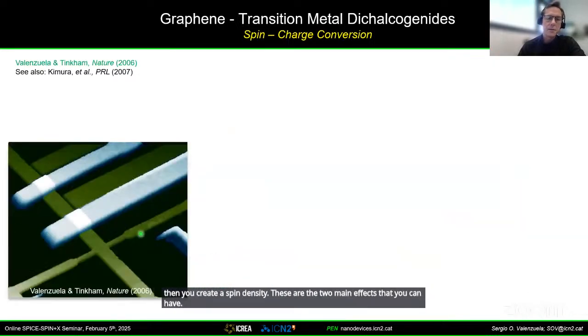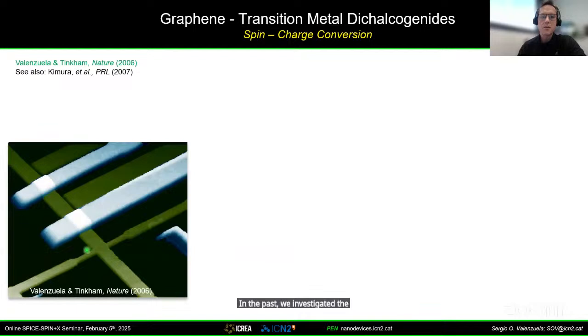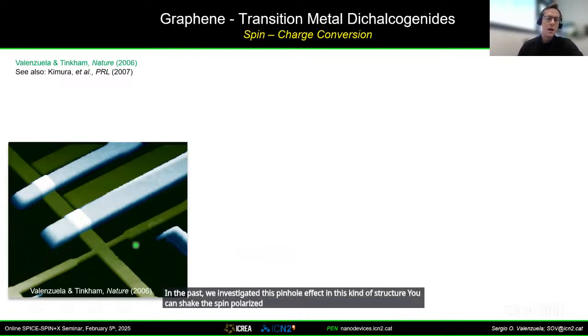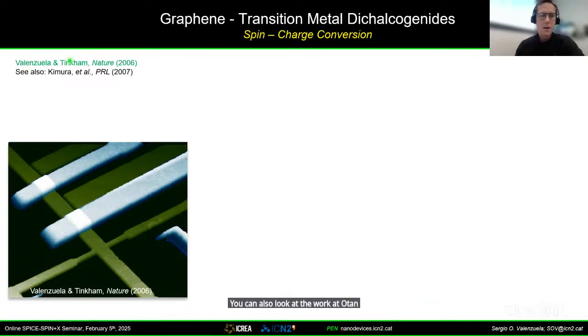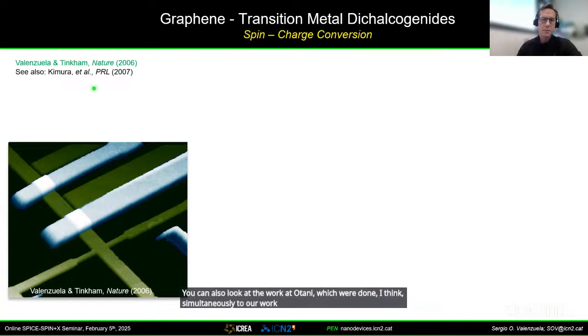In the past, we investigated the spin Hall effect in this kind of structure. You inject the spin polarized electrons from here, and you measure the voltage in a kind of Hall cross by the inverse spin Hall effect, or you apply a charge current here, and you measure the spin signal here. You can also look at the work of Otani, which was done, I think, simultaneously to our work here, but with platinum.